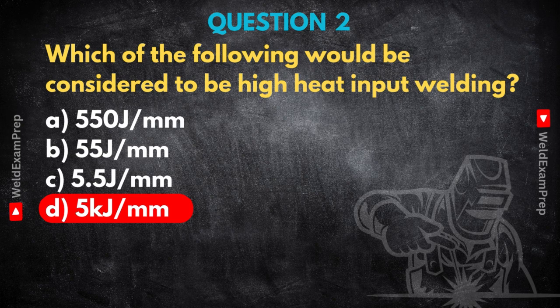And the implications of putting that much heat in are profound. It can lead to excessive grain growth, both in the weld metal itself and in the heat-affected zone, the HAZ. And that often means reduced toughness. The weld becomes more brittle, more prone to cracking. Plus, high heat input tends to increase distortion, can cause real headaches with fit-up and leave behind harmful residual stresses. So it's clearly not just about melting metal. It's about controlling the thermal cycle very precisely.